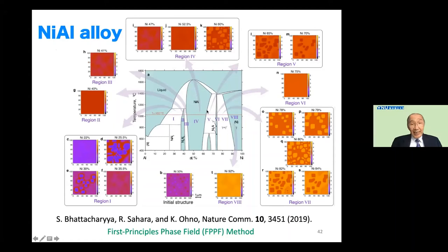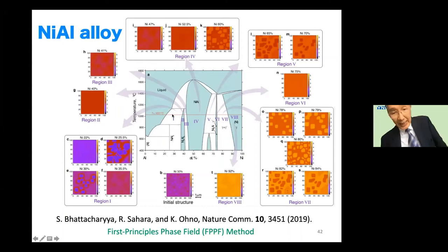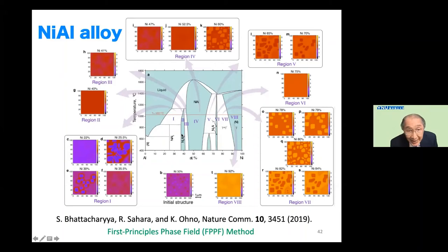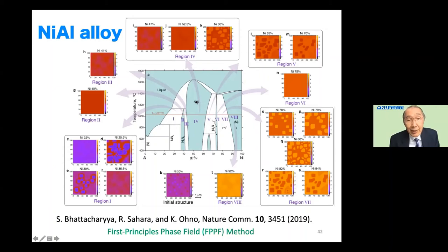The simulation is fixed at 1027 degrees Celsius. In region 1 of the phase diagram we obtain certain microstructures. In region 2 (Ni₂Al₃), we have a homogeneous result. Region 3 is also homogeneous. Region 4 is the NiAl phase — nearly equi-atomic — and if the composition is slightly different, precipitations appear within this region. Region 5 gives other microstructures.